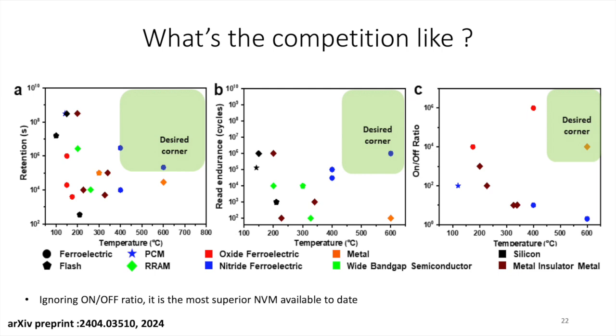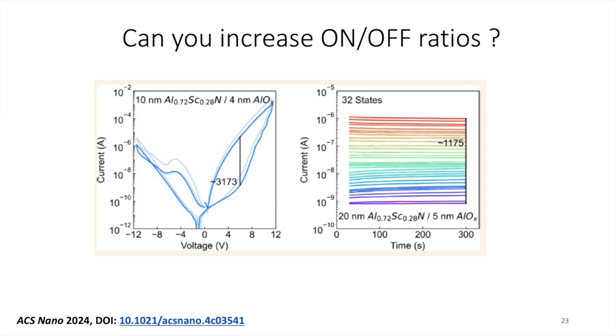So in that sense, the ferroelectric memory that we have is the most superior available out there. If you see on graph C, we don't have the highest on-off ratio yet, but this is not hard to solve. As I told you already, we have solved this problem. Technically, it's a matter of writing it up and publishing it. As a matter of fact, just yesterday we published a paper where at room temperature we have shown how to engineer these on-off ratios, and we have shown on-off ratios up to a few thousands in these kinds of ferroelectric diodes. Now it's a matter of making them on platinum or other high temperature metals and testing them at elevated temperatures, which is something we have already done and shown, but because we have not published it, I cannot mention values or details about them. But the blue point on slide 22 in graph C, which is further lower down, can be easily raised up to get into the desired corner.